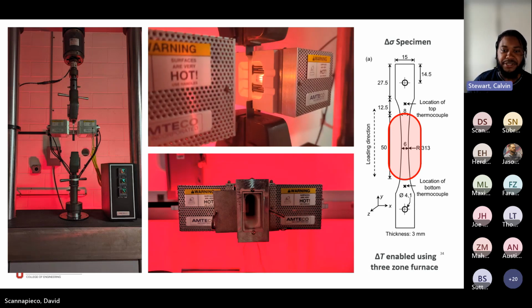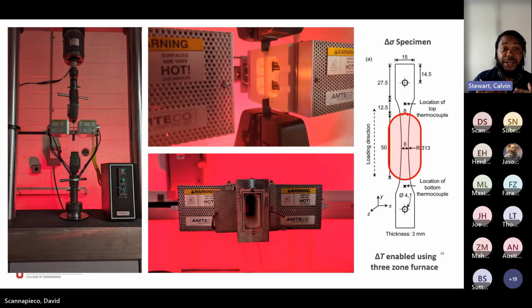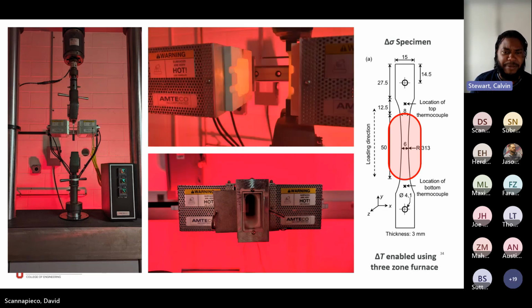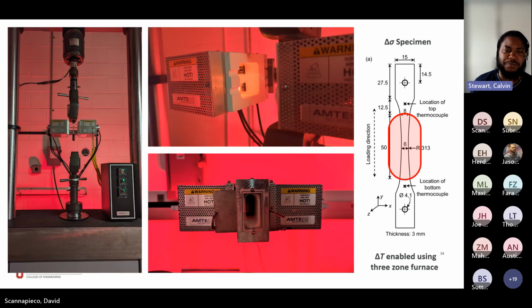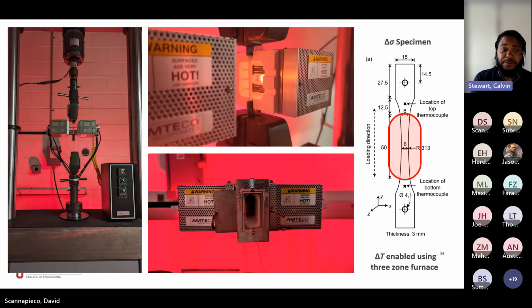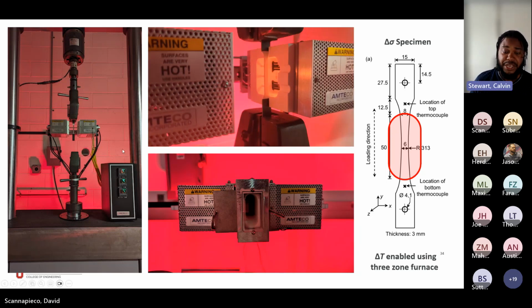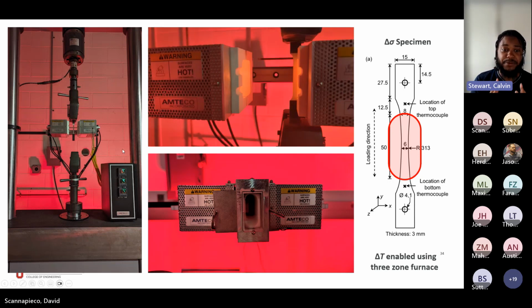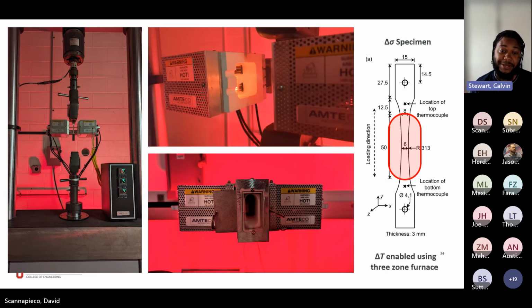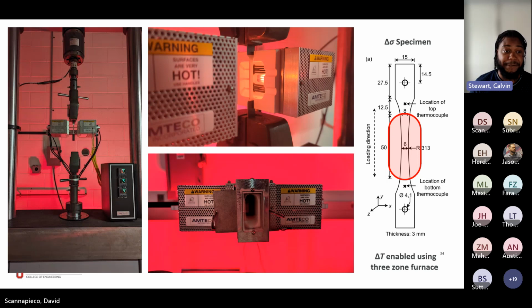Very slight radius along it that will give us a range of stresses of about 100 megapascals. It's kind of surprising. And then also, because our furnace is a 3-zone furnace, if we have a uniform sample, we can adjust the zones independently to create a temperature gradient.